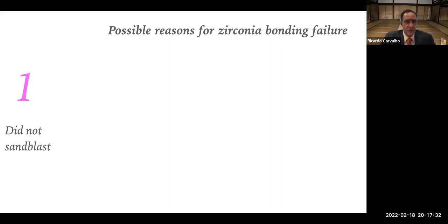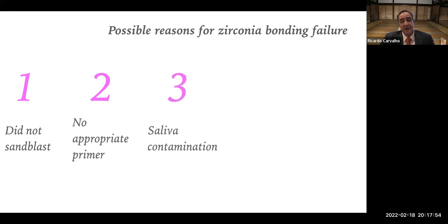So what are the reasons? Well, probably the zirconia was not sandblasted. So sandblasting is, let's say, an important step. The primer was not applied, or you did not apply an appropriate primer. Again, it does not help to apply silane on zirconia. Saliva contamination is a big issue, as we know.